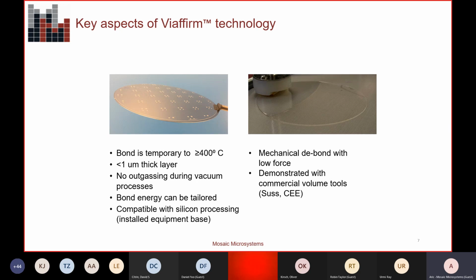So if you want an easy debond for the next step, you can tailor that bond energy lower. If you want to put a very high stress coating on, you can ramp up that bond energy and get a little bit more stronger force holding that wafer down to the handle. So that can be a very important aspect as well. And again, by and large, we've shown to be very compatible with existing PVD, CVD, etching, cleaning, CMP. We haven't had a single issue at CMP with any debond. We've had very good results with CMP of the copper layer, but also of smoothing the glass and thinning the glass. So it's very robust in shear and a little weaker in tension, which allows for the debond.